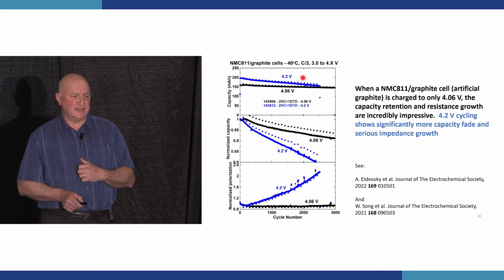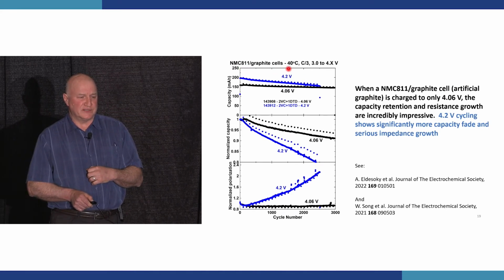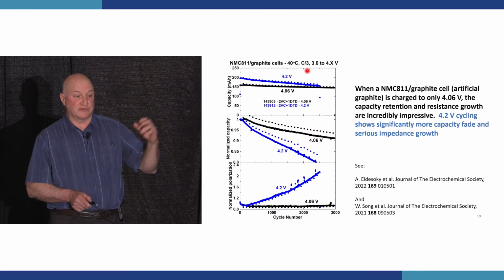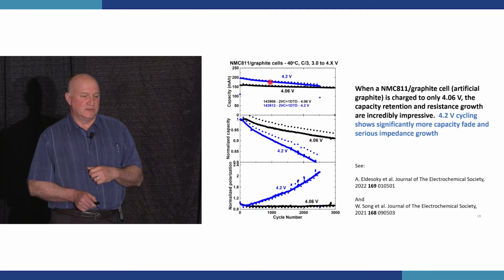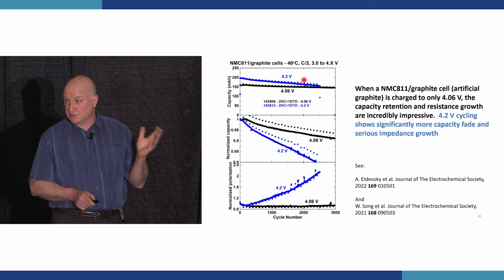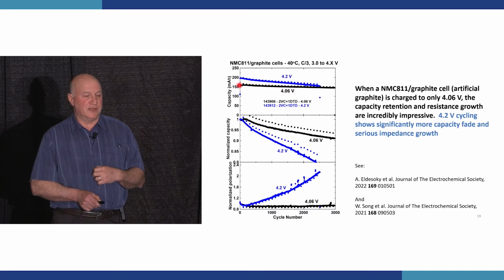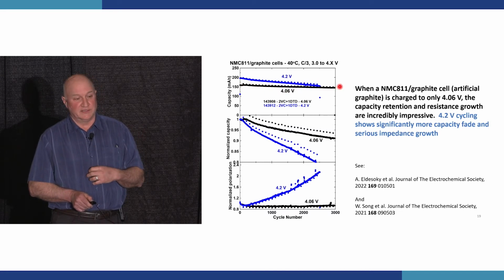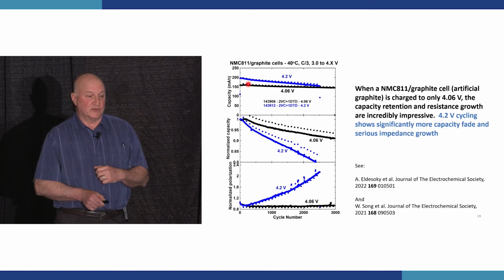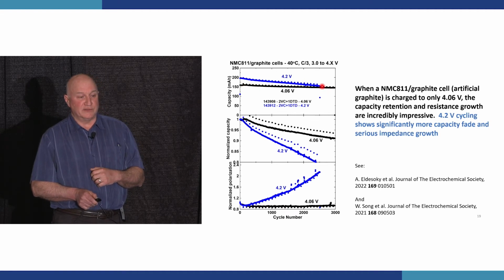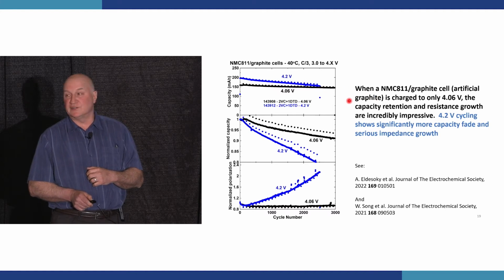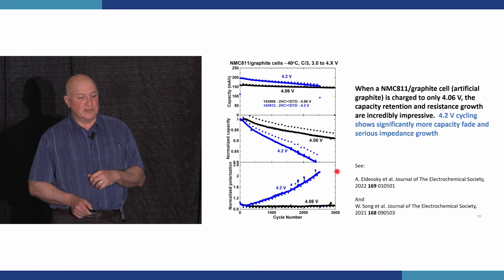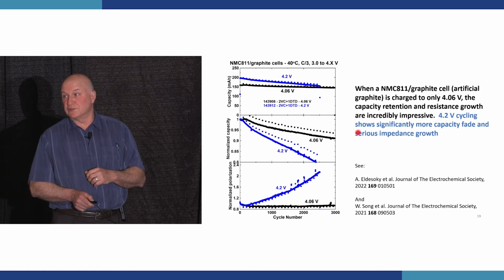So here I'm showing you data for NMC 811 graphite cells tested at 40 degrees C with a 3-hour charge and a 3-hour discharge. The blue, they're cycling to 4.2 volts, where they're undergoing that large volume change every charge-discharge cycle. And the black, they're going to 4.06 volts, where they avoid that large volume change. And of course, the lower voltage gives smaller capacity, but after these 2,500 cycles, they're virtually the same. And if the tests continue, the blue would fall under the black, and the black would be better. So this is 3,000 charge-discharge cycles, takes about 2 years, okay?